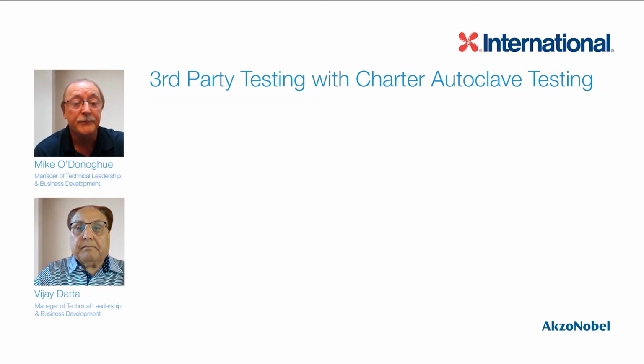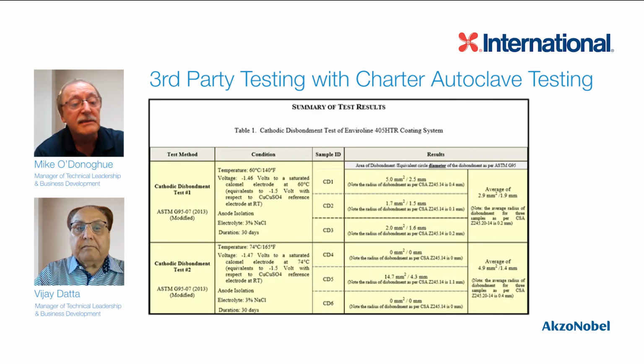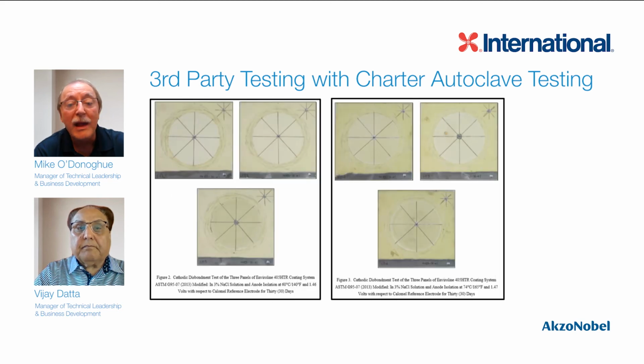We also do the cathodic protection testing, by looking at the disbondment, and we obviously do very well. This particular one is ASTM G95, but we've done the CSA Z245s as well. And what we see with the cathodic disbondment testing is very small amounts of radial disbondment, which are fully in compliance with the testing criteria that are required for that testing.